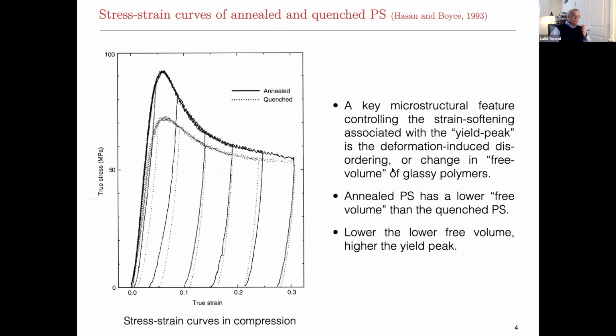In fact, the yield peak depends in a sensitive manner on the prior heat treatment of the material. If you take the material above the glass transition temperature and quench it, then it has a higher degree of disorder or free volume, and the yield peak is lower. If you anneal the same quenched material so that there are more tightly packed atoms, the yield peak is higher. And this could be of the order of 20 or 30 megapascals just from small amounts of heat treatment.